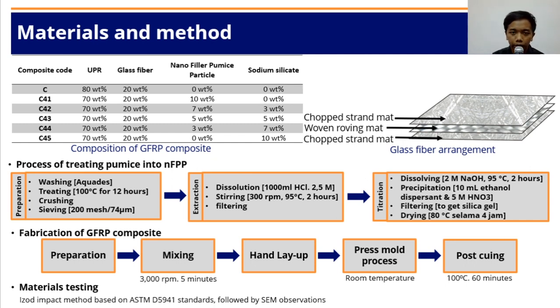The first is the C composite, which is a composite without the use of filler. The second is the composite C41, which is a composite containing 10% nanofiller pumice particle without sodium silicate addition. Next is the C42 composite, which contains 7% nanofiller pumice particle and 3% sodium silicate. Then the C43 composite contains 5% nanofiller pumice particle and 5% sodium silicate. The C44 composite contains 3% nanofiller pumice particle and 7% sodium silicate. And the last one is the C45 composite, which contains 10% sodium silicate without the addition of nanofiller pumice particle.